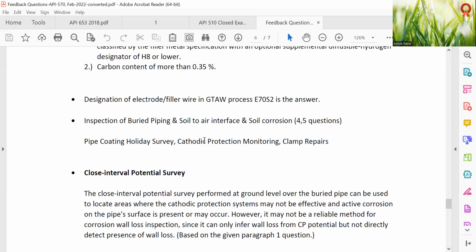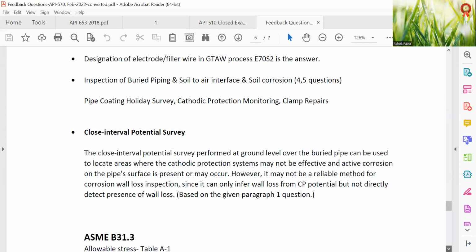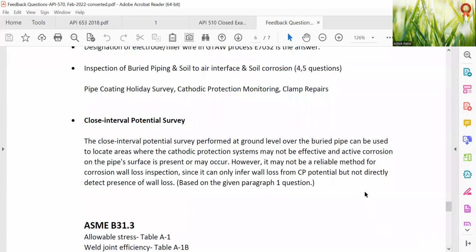Inspection of buried piping, soil to air interface, soil corrosion, 4-5 questions. Pipe coating holiday survey, cathodic protection monitoring, clamp repairs. The close interval potential survey performed at ground level over the buried pipe can be used to locate areas where the cathodic protection system may not be effective and active corrosion on the pipe surface is present or may occur. However, it may not be a reliable method for corrosion wall loss inspection since it can only infer wall loss from CP potential but not directly detect the presence of wall loss.